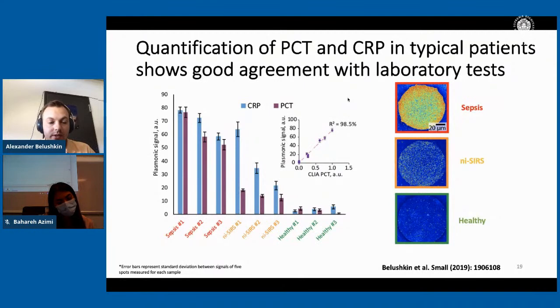So what we did first, we quantified the 2 biomarkers, PCT and CRP, for the most typical patients of the 3 groups. As you can see here on the right, for different levels of PCT, you have very different densities of nanoparticle binding, which allows us to quantitatively detect the level of the biomarker. At the same time, we mapped the results of the plasmonic signals, whatever we get with our system, to the gold standard CLIA, which is chemiluminescent immunoassay, the tool that they use in the hospital for performing those tests on commercial machines. And we got pretty good agreement between both, so this was also very encouraging.